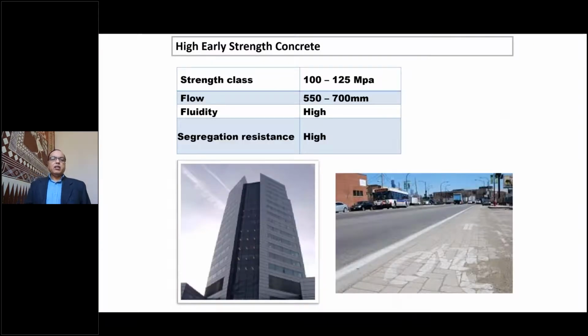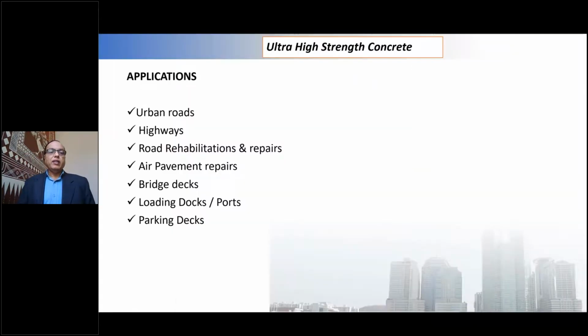And in this case, we are talking of M100 and above. M100 and above up to M125 grade of concrete. The flow, that is the slump, is 550 to 700 millimeters. The fluidity is very high, but it doesn't mean that there will be bleeding and segregation. Segregation resistance and bleeding resistance is also quite high. Where do we use this ultra high strength concrete? It can be used in urban roads, highways, rehabilitation works, airport pavement repairs, bridge decks, and so on.